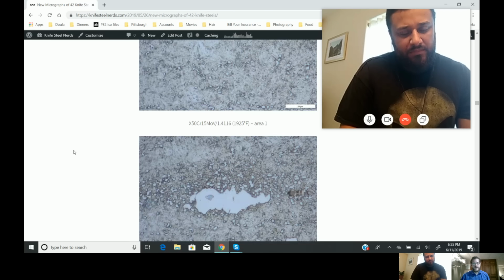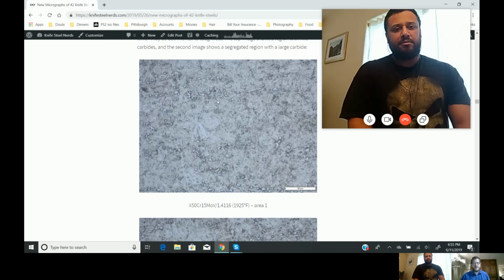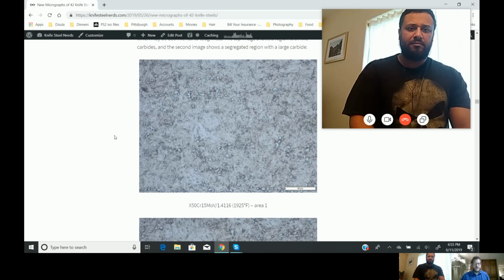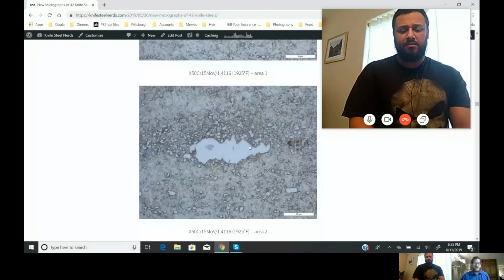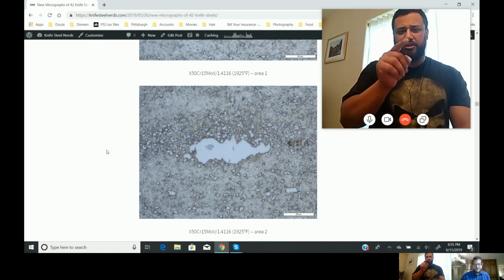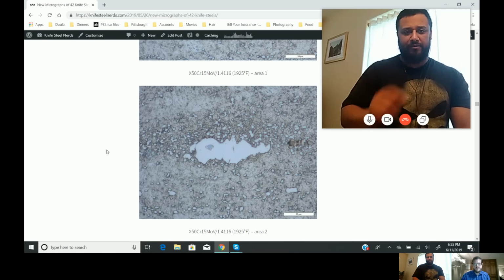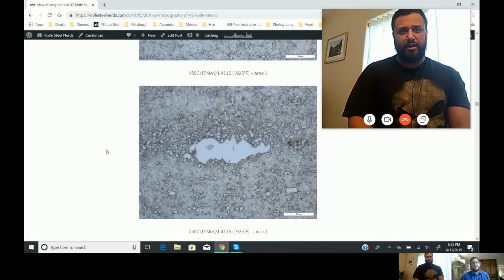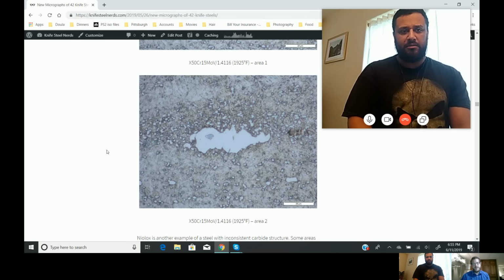So we tested the toughness of this steel, and it was not that great. You'd think at 56 Rockwell and with these fine carbides, it'd be super awesome. It's only got 50 points of carbon. But when you've got occasional huge carbides in there, then those are easy places where cracks start. And this is interesting too. This actually has lower carbon. You said 0.50 on this, and we still get this big old honker in there, huh? Yeah, and I'm not sure exactly why they can't eliminate these with forging. Maybe it's the high chromium content. These are 15% chromium versus 13 in an AEBL. So maybe that just makes certain carbides more stable.